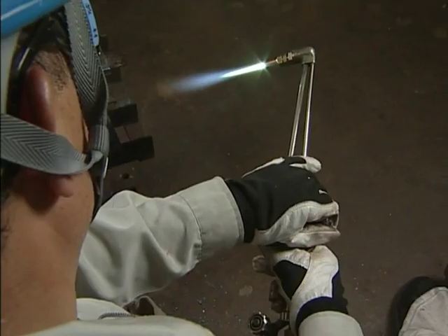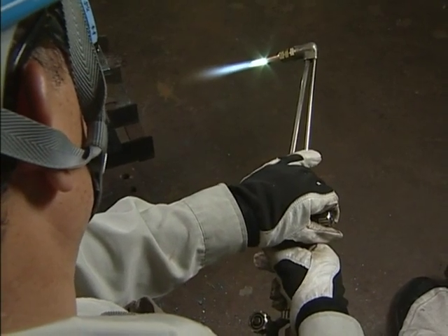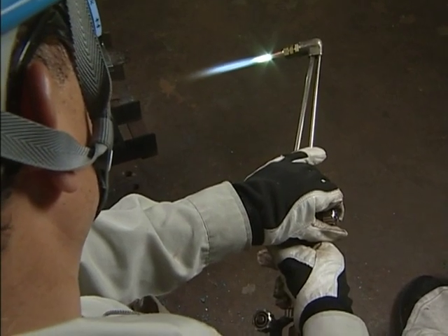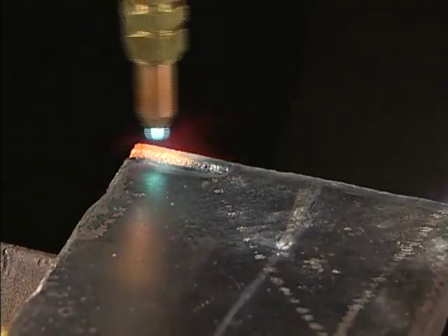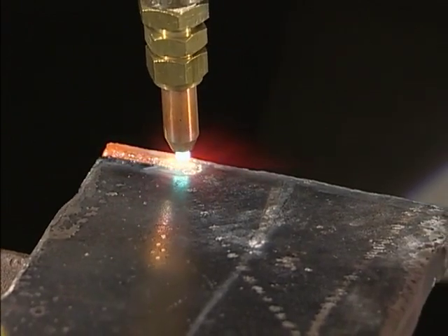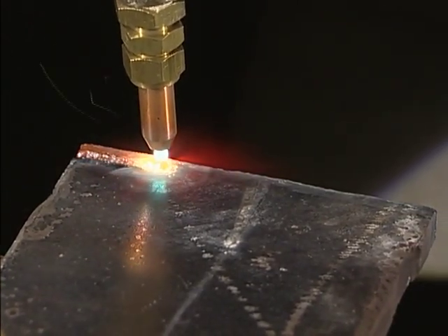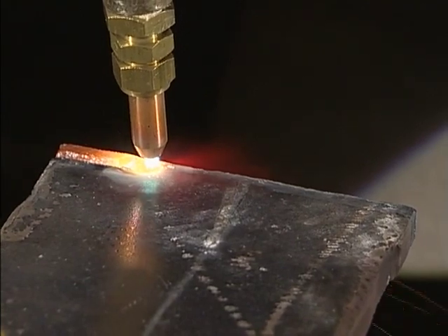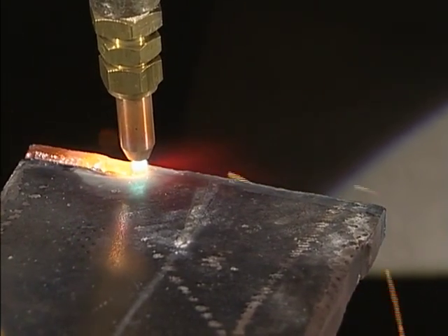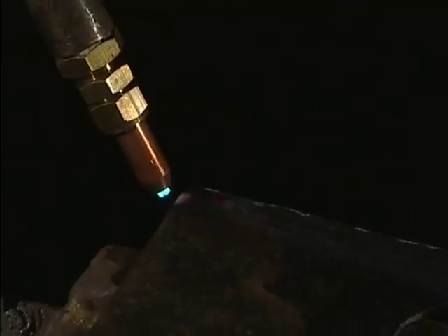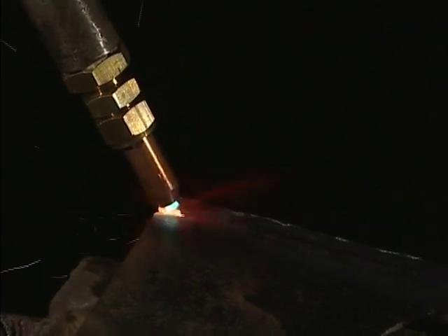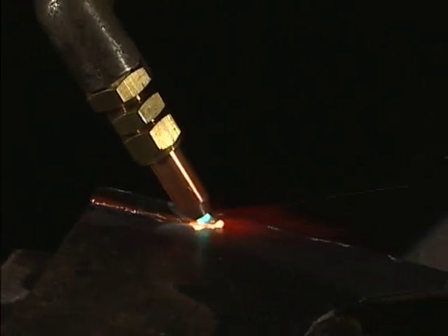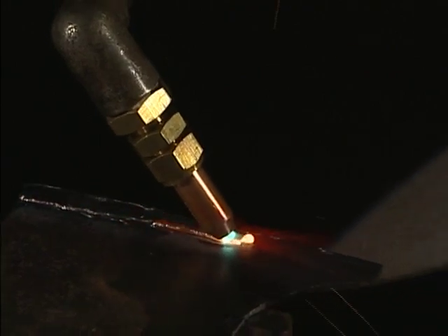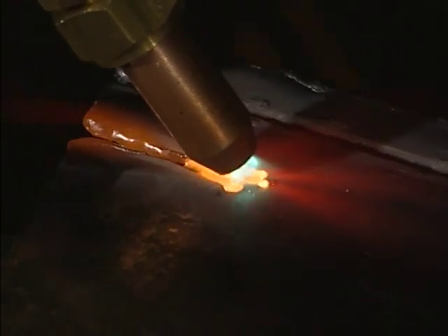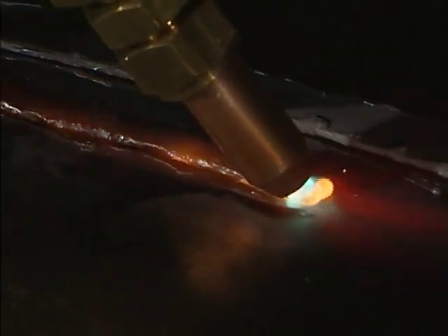In the event cutting stops halfway through, close the cutting oxygen valve immediately and resume the operation from the preheating stage. For a thin sheet, incline the torch tip markedly in the direction opposite from the cutting direction. Guard against backfiring, which can occur if the torch tip becomes clogged as a result of coming into contact with the material's surface.